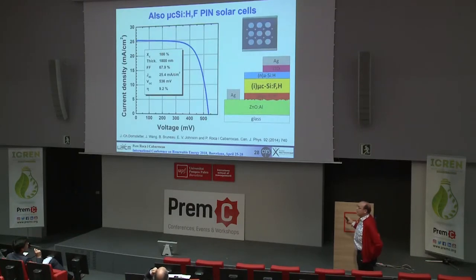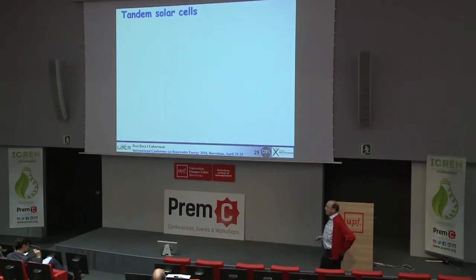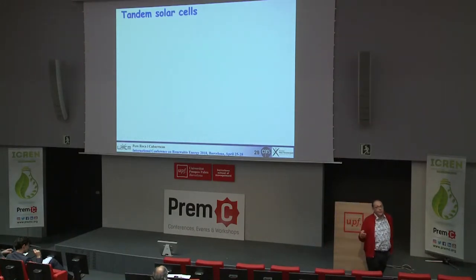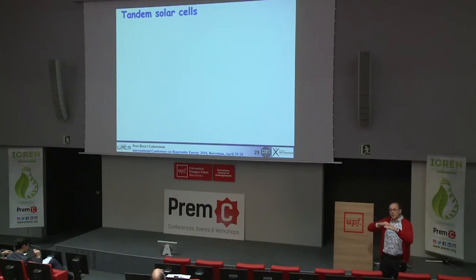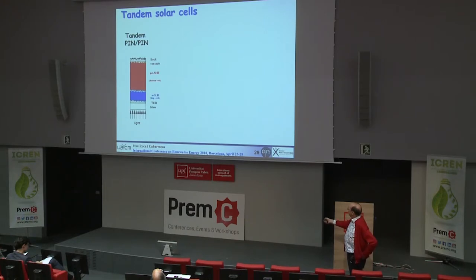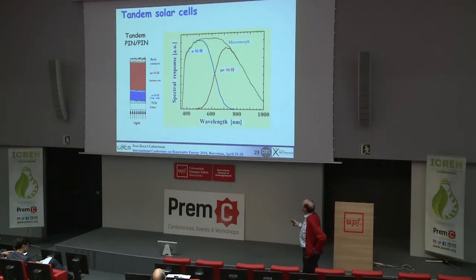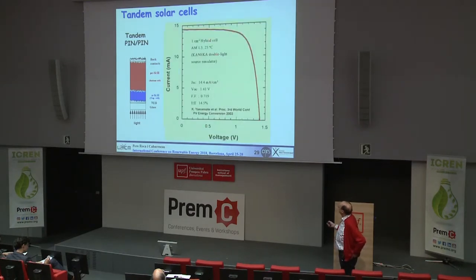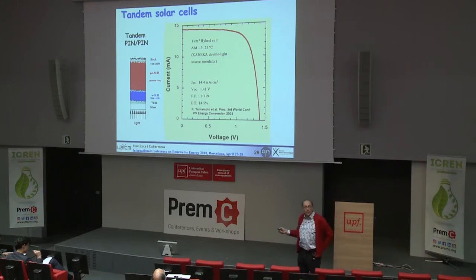We can make microcrystalline material, so we can make a material which is ordered, small domains. And if we combine the amorphous and microcrystalline, we can make a tandem solar cell. It's again, you just put the substrate, PIN, PIN, you stack the cells here: glass, TCO, PIN, second PIN. And with that, you are going to cover a wider range of the solar spectrum. And by doing that, you are going to get a tandem device. So the efficiency is going to go to 14.5-15%. So now we are increasing efficiency.